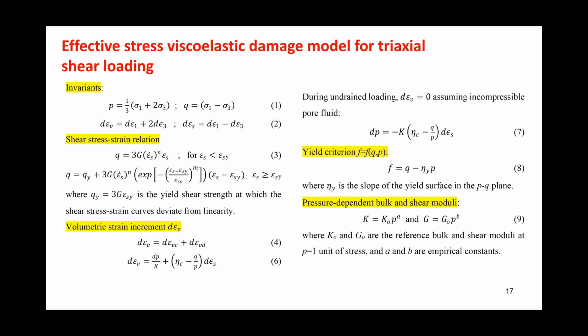Okay, and the dilative volumetric strain. So this is the compressive volumetric strain is equal to the change in the mean stress divided by the bulk modulus. And the deviatoric strain is as a result of the shear strain increment. We have here the shear stress ratio Q over P, and Eta sub C is equal to the slope of the phase transformation line at which the material changes from contractive to dilative response.